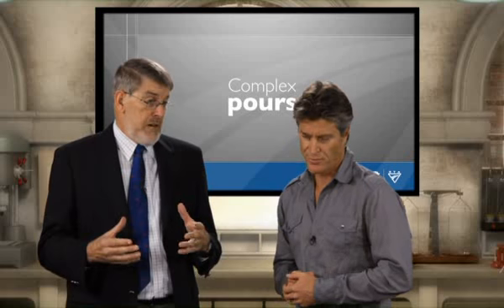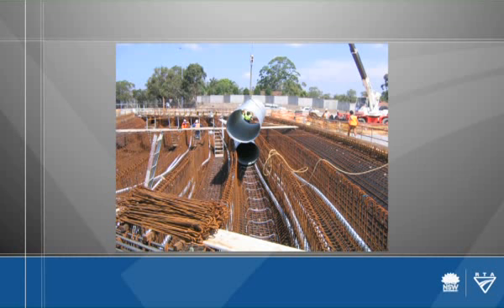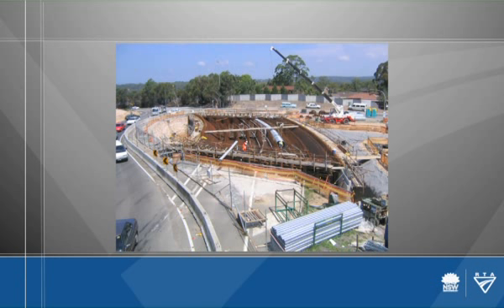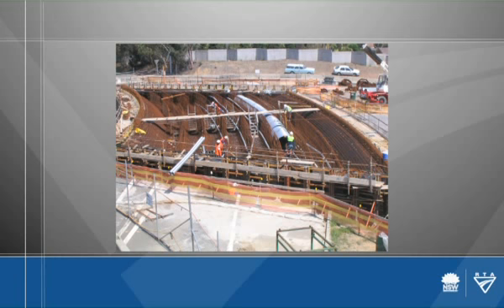The other issue that comes up is in some members we use what we call a void former, and there's a real risk here. You can imagine if you've got a large circular void, there's a real danger of air being trapped underneath that void former. So when it comes to this sort of construction, it has to be done very carefully, and we've got examples where there's been large areas of void because the concrete never got under the void. We don't want that. Exactly.